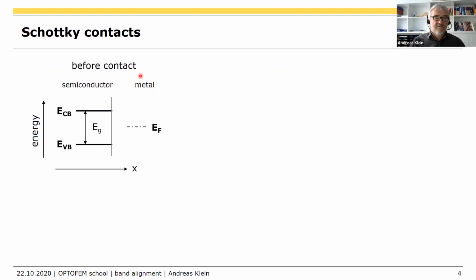All right. So we are talking about Schottky contacts. That means we have a semiconductor with a valence band maximum and a conduction band minimum. You will notice that there is no vacuum level here, because that's not relevant for the barrier and for the electrical properties at all. Then we have a metal, and for the metal, we don't draw the valence and conduction band. We, in principle, simply draw a line, which is the Fermi energy. That's the highest occupied state in the metal.